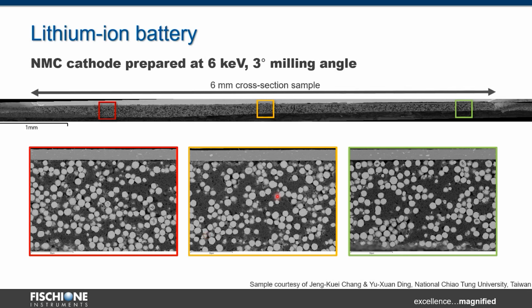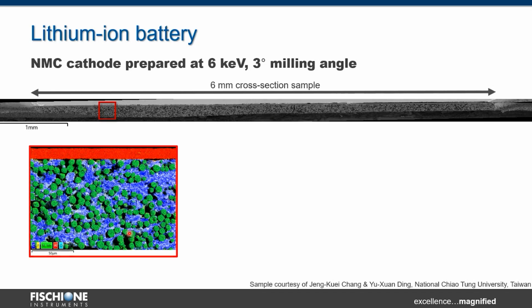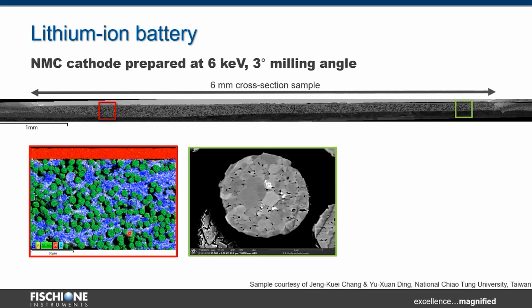If you go from the edge of the cross-section to the center, you have the same quality of sample preparation, as you can see here. If you zoom in, you see nicely the aluminum electrode, and you see here the NMC particles. And of course, you can do any analytical work on that, EDS, to get chemical composition. You can observe individual particles, see grain shapes, grain size. This bright contrast shows the nickel segregation close to the center of the particle.